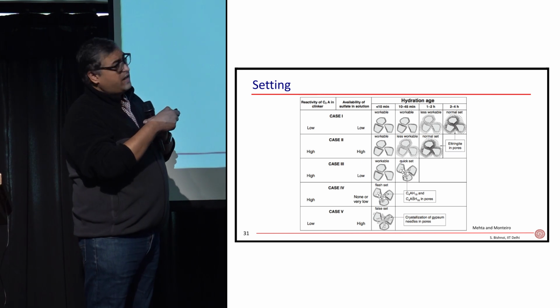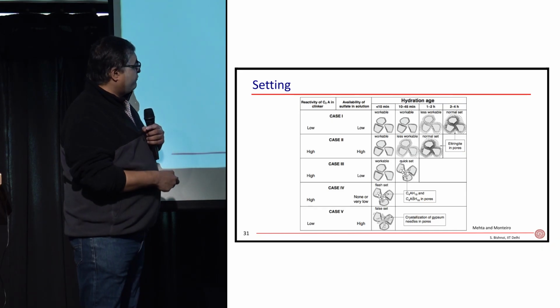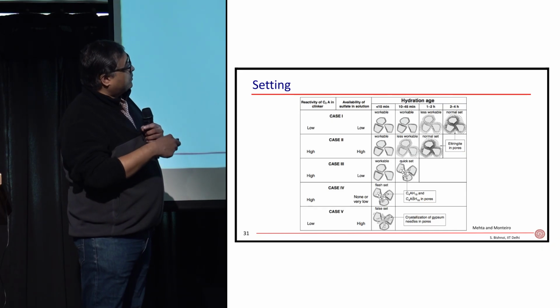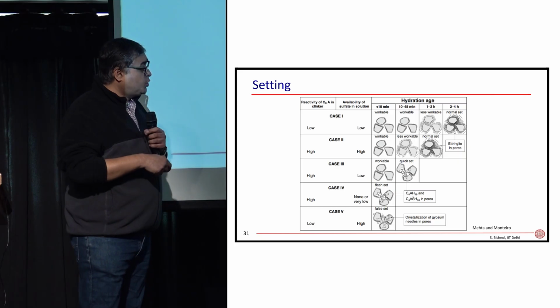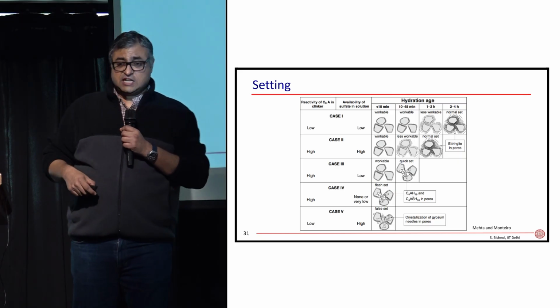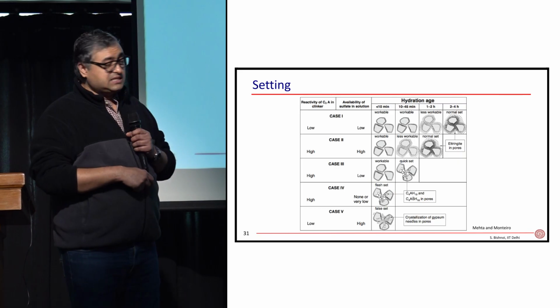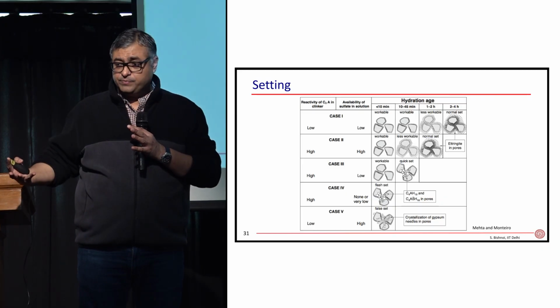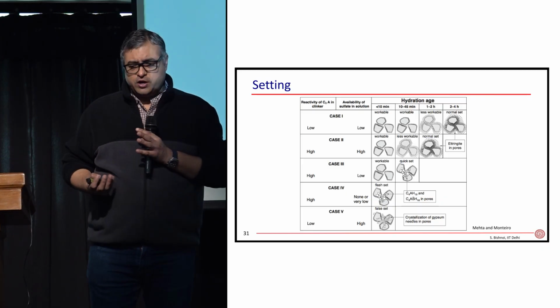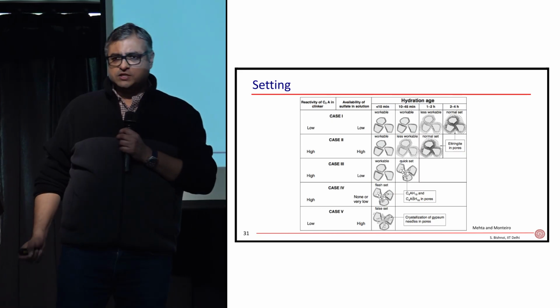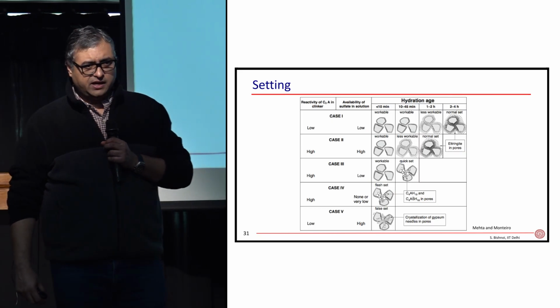If you have a high amount of alumina, you need to put more gypsum. If you have less alumina, you need less gypsum. If you put too much gypsum, even with less alumina, some of the gypsum may precipitate. This also happens if you've got what is called hemihydrate or anhydrite in your cement.